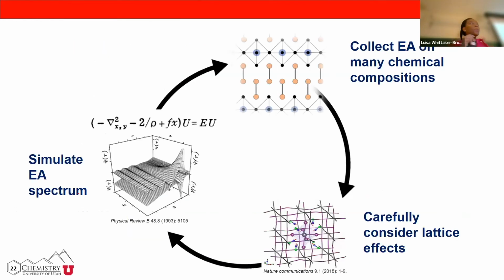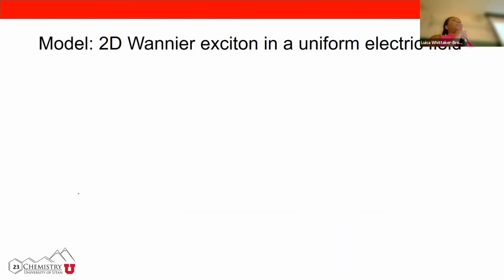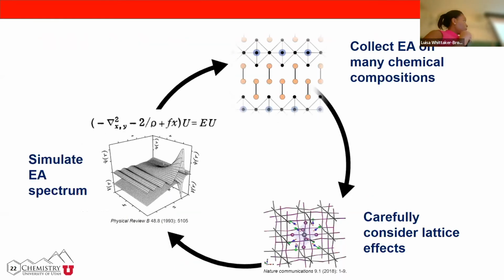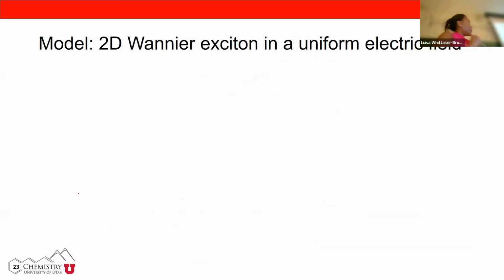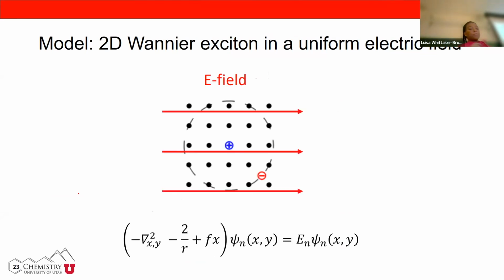So what we ended up doing is that we collected a lot of electroabsorption data on many compositions of metal halides. We put in lattice effects and we simulated the electroabsorption spectrum by solving some equations here. So let's look at the model. The model is very simple, right? We can treat it as a hydrogen model, right? So you basically have a hole and an electron.